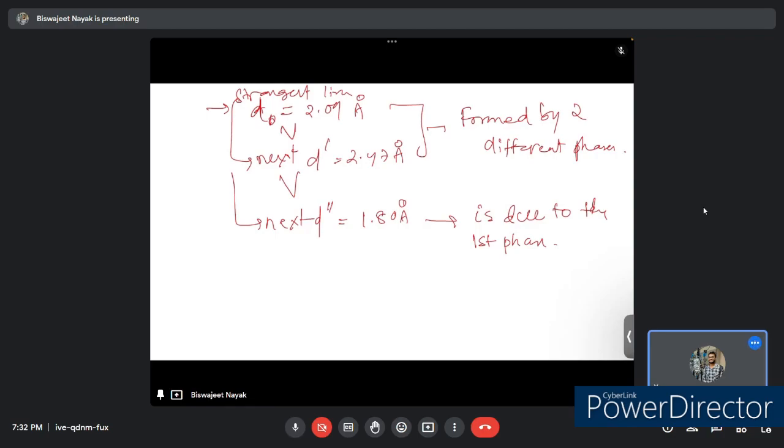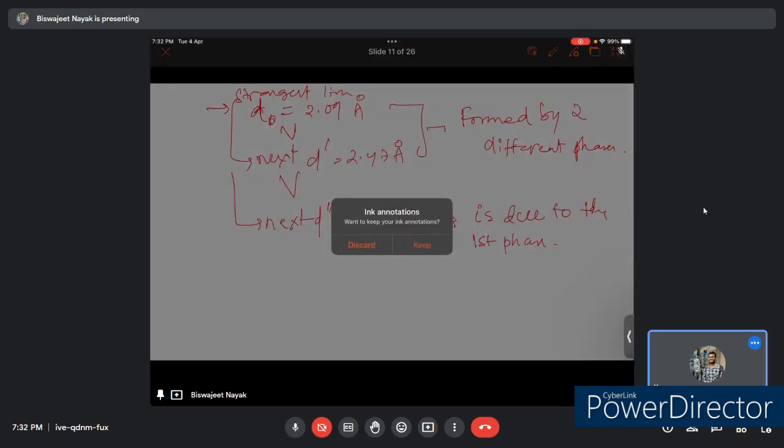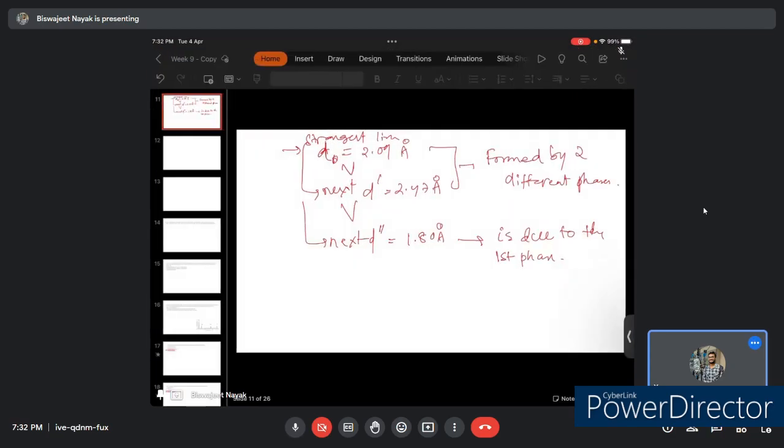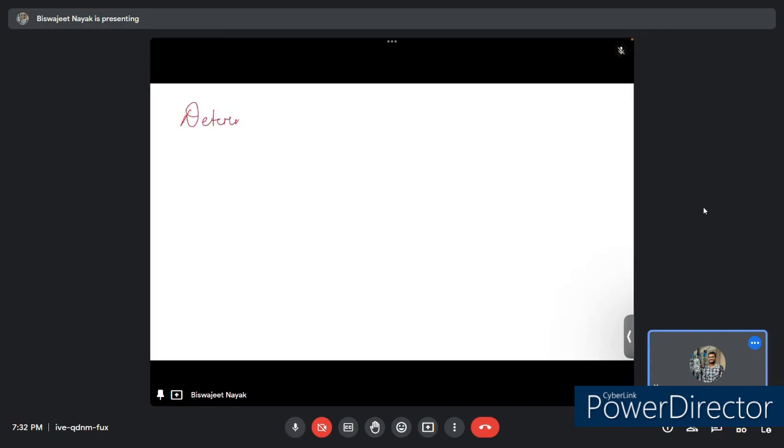Such patterns can be untangled by separating lines which agree in d value with those of unknown phases, the observed intensity of any superimposed lines being divided into two parts, one assigned to the unknown phase and the balance, together with the remaining unidentified lines, iterated as we solved it for single phase material.